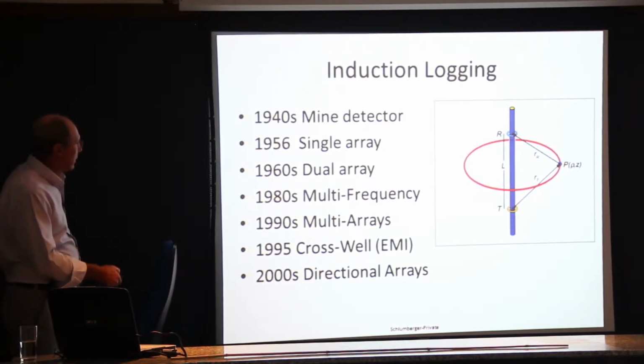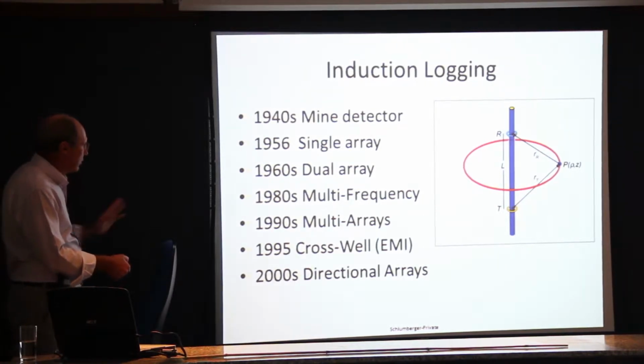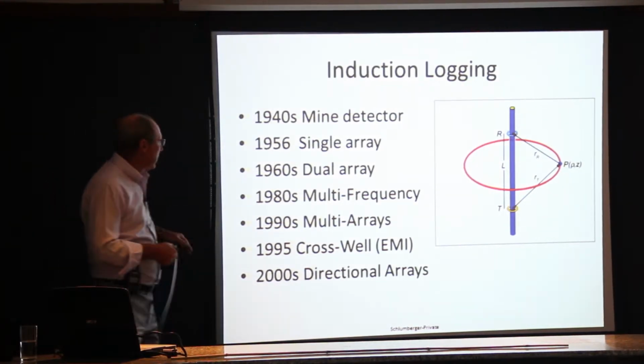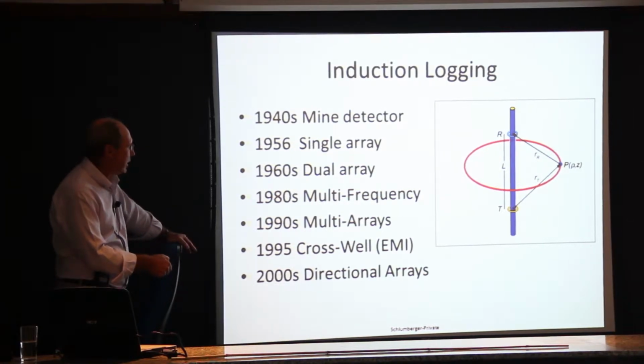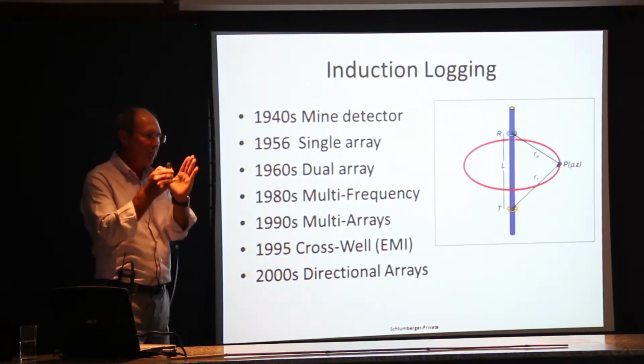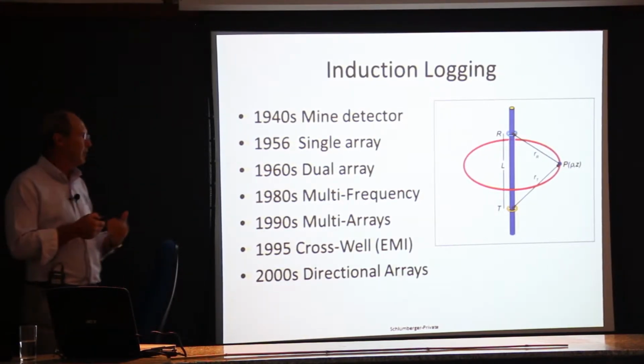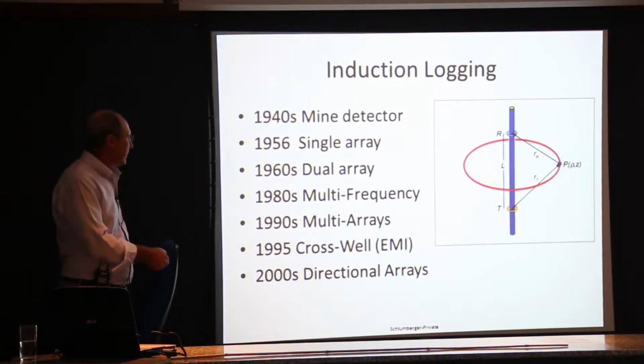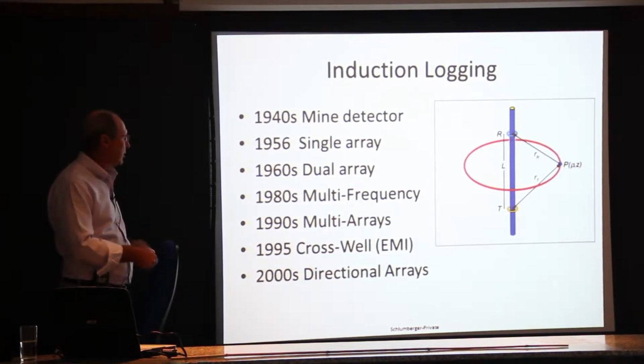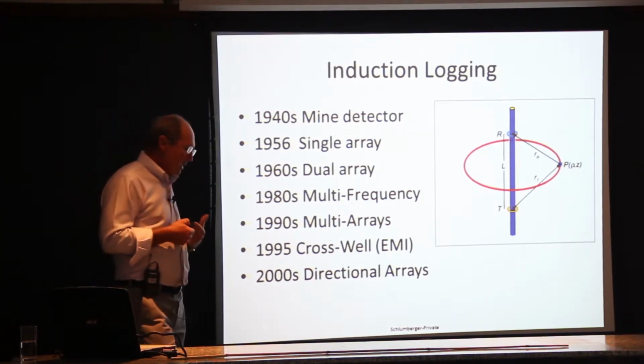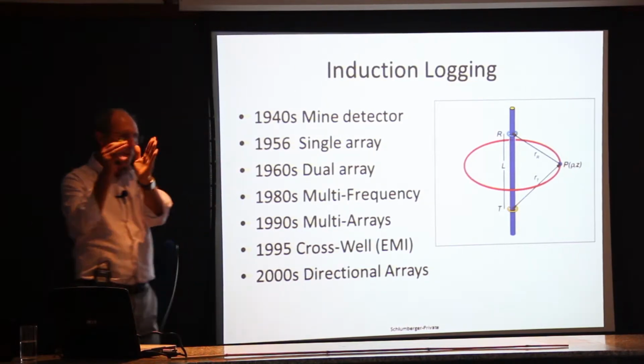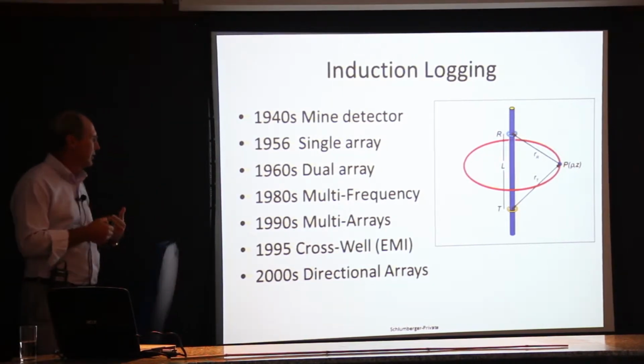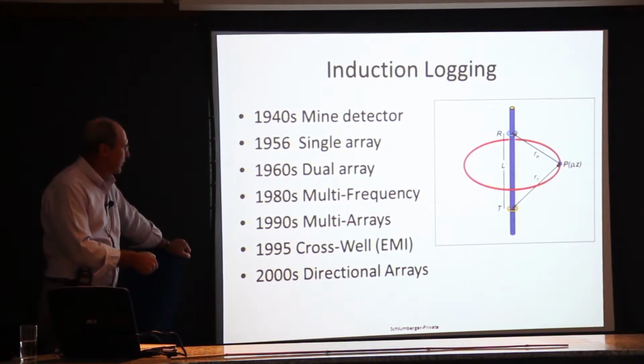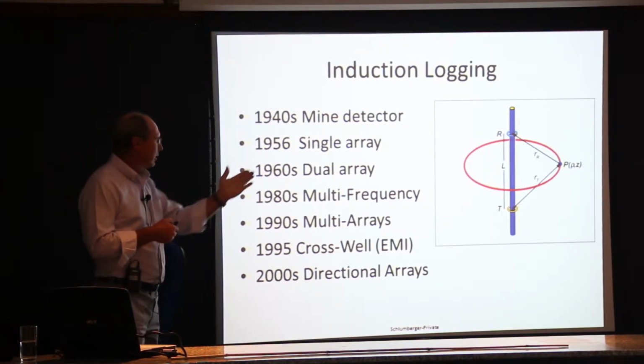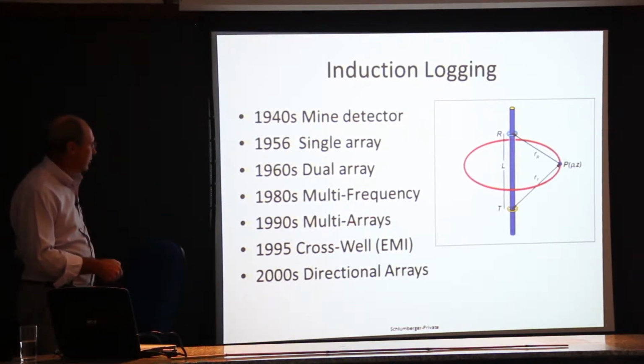So in terms of the evolution of induction logging technology, it went from a single array in the 1950s to 2 arrays, where one was deeper, one was shallower. That eventually led to multi-frequency arrays, where you could play with the fact that the higher frequencies didn't propagate as deep, so you could look shallower in the formation based on frequency. But eventually it led to multi-arrays, where most of what we call subtraction is done. So if you want to isolate one particular depth in the formation, you can actually use computer processing now to subtract out the effect of other arrays to isolate certain depths of investigation. And so this works very well.